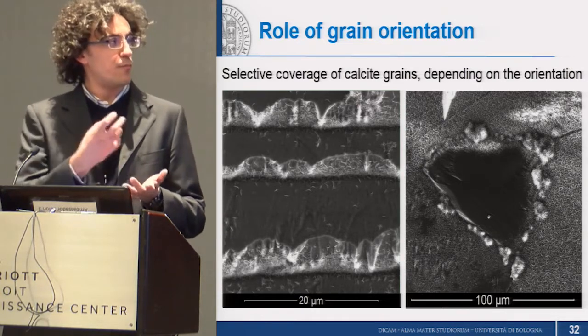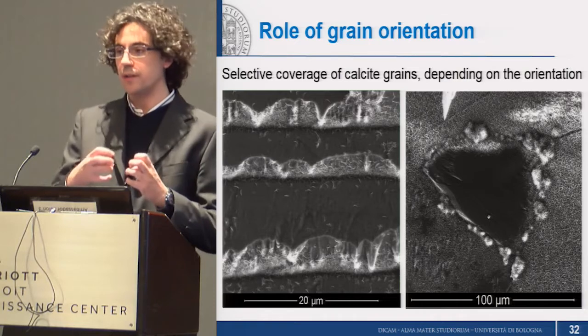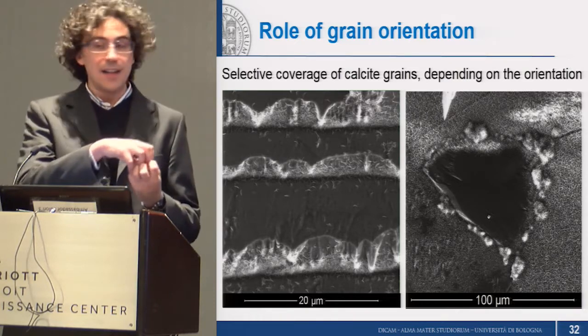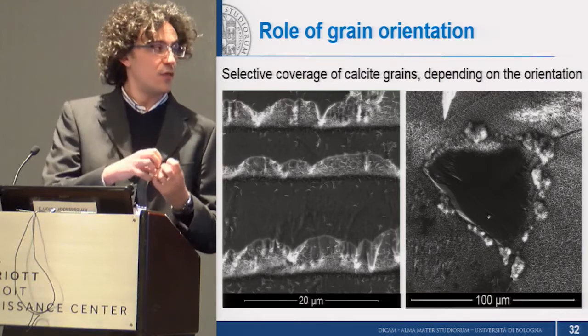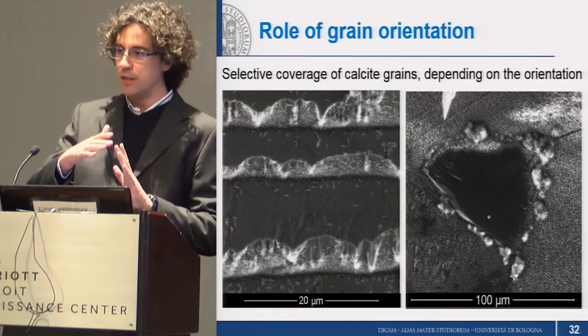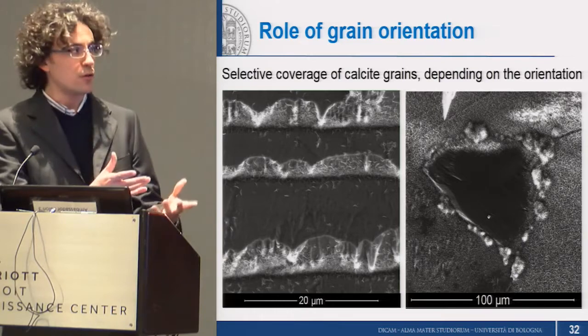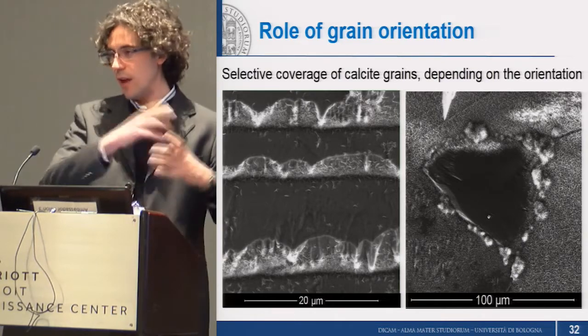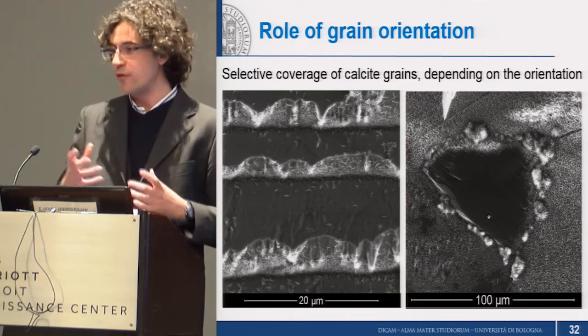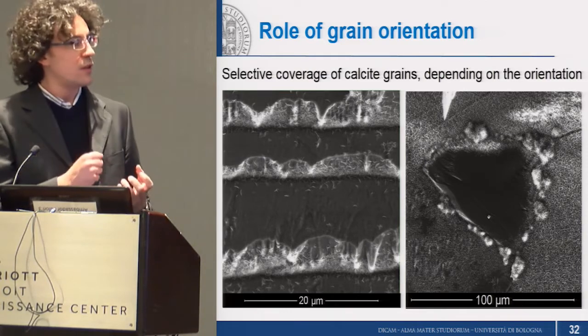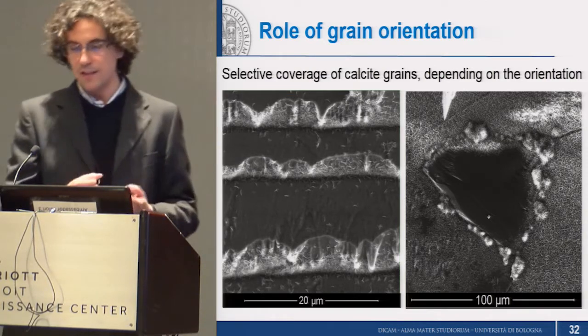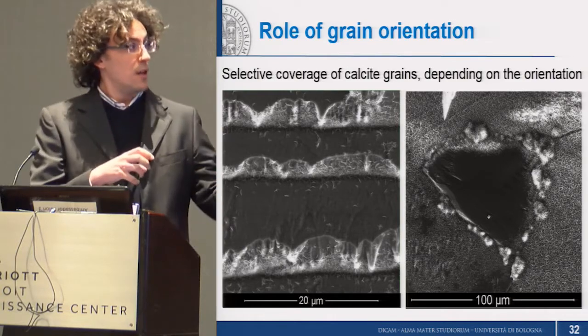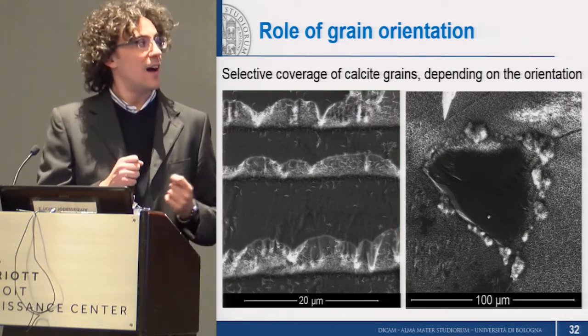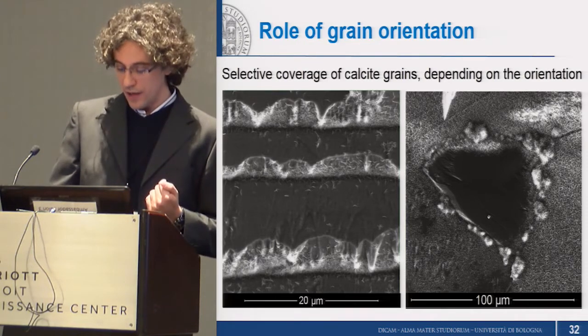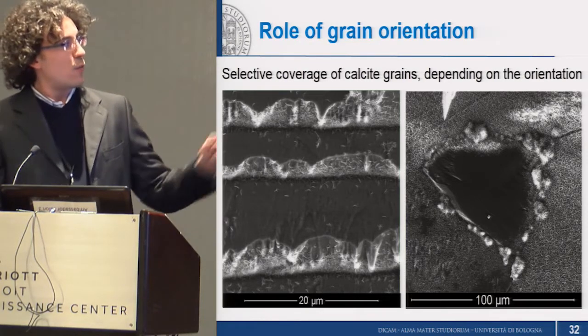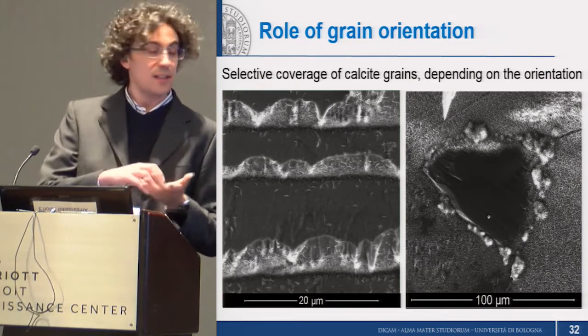According to literature, people were able to get epitaxial growth of HAP on top of calcite, but this could only take place for very specific orientations of both minerals. But unfortunately, in our case, because we are not working with a single crystal of calcite, but we have hundreds of crystals with random orientations, this is unfortunately not always possible. So for those grains that have the least favorable orientation, it's at the moment quite hard to get a sufficient covering.